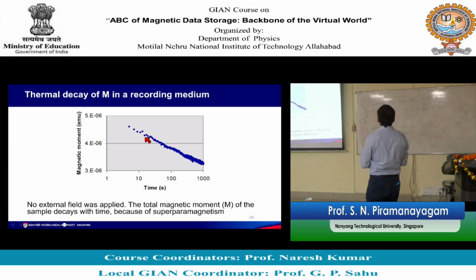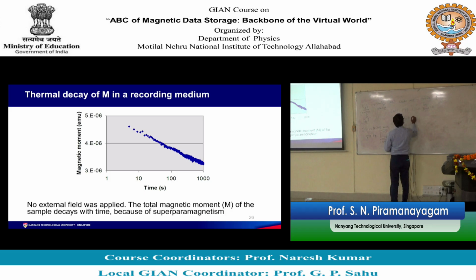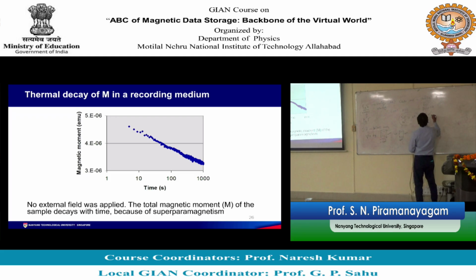In this particular sample, the ratio between KUV and KBT is roughly 45 or something. The KUV by KBT determines how stable the magnetization is. The ratio between the magnetic anisotropy energy that retains the information versus the thermal energy determines the thermal stability. And if you make this number 60, then the data will be stored for 10 years.